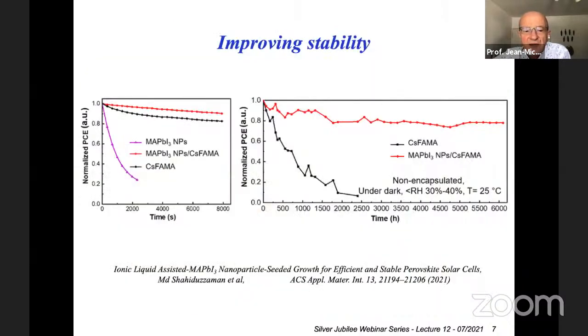The technique we were developing with this seeded growth, starting from an ionic liquid prepared nanoparticle, allowed us to fabricate stable materials. Stability is always an issue with solar cells and photodetectors. And on the left, you see a figure of stability of our compound. Our technology is the one pictured in the red curve, with respect to different technologies, which are also well approved, not using the seeded growth from nanoparticles. We get a better stability under illumination, and a better stability.